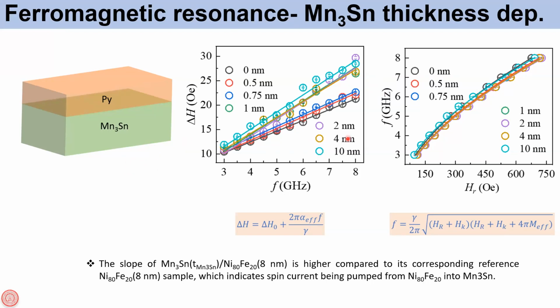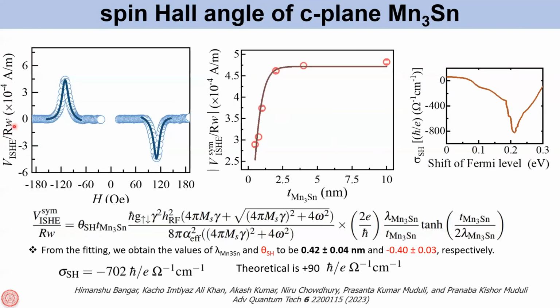measurements. These are the FMR measurements from which we determine the Gilbert damping constant and M effective. And most important, this inverse spin Hall effect, where you see that very nice symmetrical curve which changes sign, which is an indication that this is due to the spin Hall effect. And when you do the thickness dependence and fit it, you can calculate the spin Hall angle and spin diffusion length. The spin diffusion length is found to be 0.42 nanometer, which agrees with what the literature has reported.